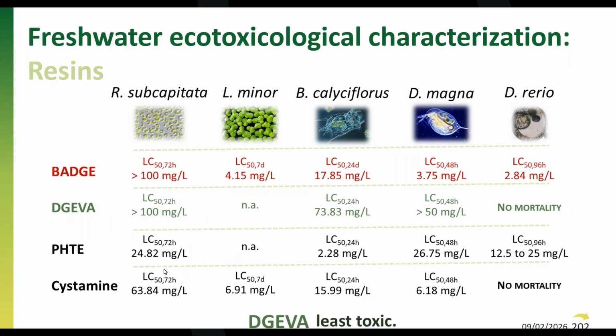So taking this into consideration, we can see in this table that DGEVA, this bioresin developed within the Bio-Uptake, was the one that exhibited the highest values of LC50s, and indeed for D. rerio it had no effect. So this was the resin that induced the least toxicity for all these aquatic species, which of course is a positive result considering that we want to move to the bio-based materials. Next slide, please.